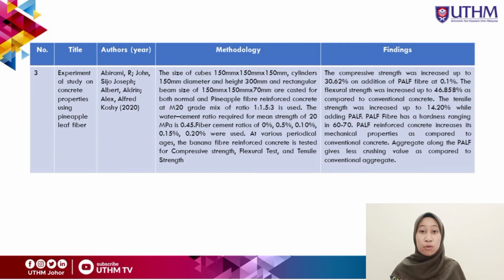Fibre-cement ratio of 0, 0.05, 0.10, 0.15, 0.2% were used. At various periodical age, the pineapple fibre reinforced concrete is tested for compressive strength, flexural test, and tensile strength. The finding is the compressive strength was increased up to 30.62% on addition of pineapple leaf fibre at 0.1%. The flexural strength was increased up to 46.858% as compared to conventional concrete. The tensile strength was increased up to 14.20% while adding pineapple leaf.